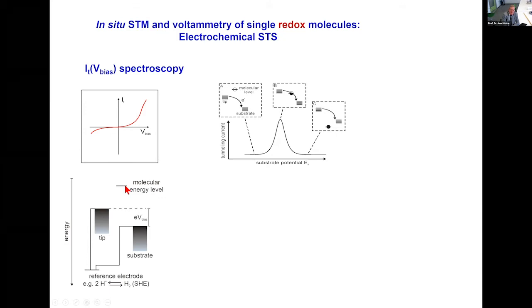For the alkane thiols, these levels are way out of what is accessible. So the mechanism of electron transfer from the tip to the substrate or vice versa is tunneling through the barrier constituted by the highest occupied molecular orbital. But for a redox molecule, this level is much lower, so it is accessible when we change the potential. Here you can see, if we change the bias voltage at fixed tip potential, then we change the substrate potential positively, we increase the bias voltage, so more and more levels become available for electron transfer. And that means the current will rise, as we see it here.